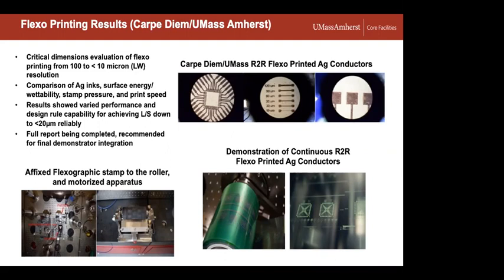So we got pretty good fidelity, had to be very careful about the speed of the process and other parameters on both the substrate and the ink, but we were able to reproduce pretty good fidelity patterns. I think in the upper right, if you look at the middle pattern, those are some test features that we had printed. And you can see you're getting down to 30, 20, even 10 microns. It's getting a little thin there, but you're able to get those types of features in such a printing technique. So again, it gives us different tools and different weapons we can use when we're trying to print really challenging line widths, as well as achieving a reasonable line conductivity or line resistivity.